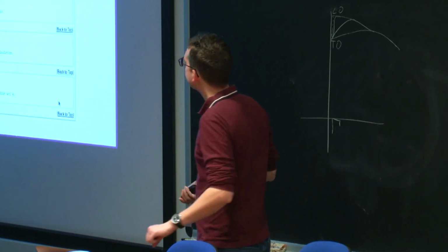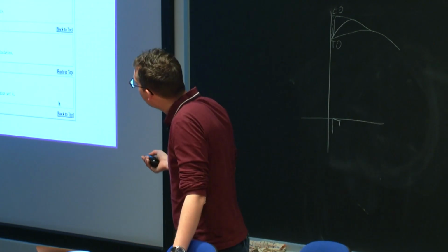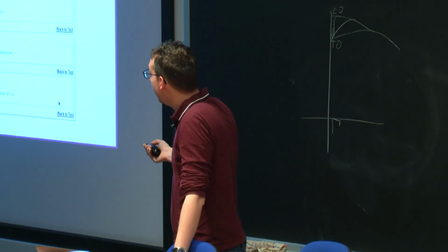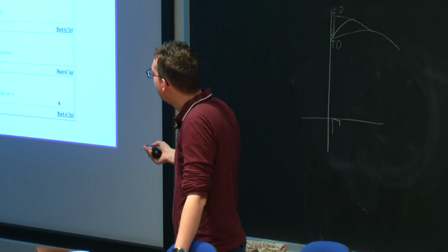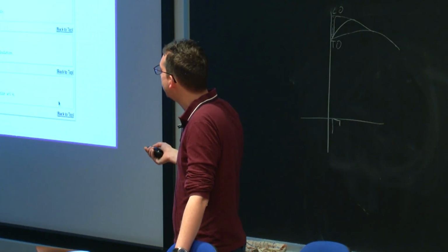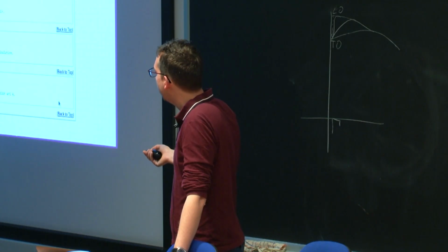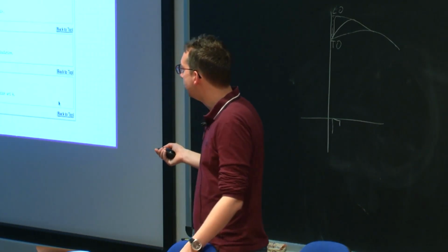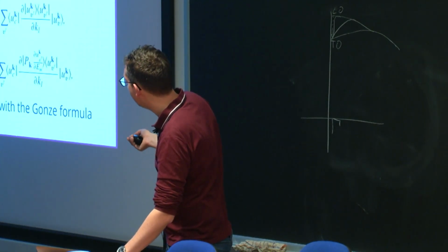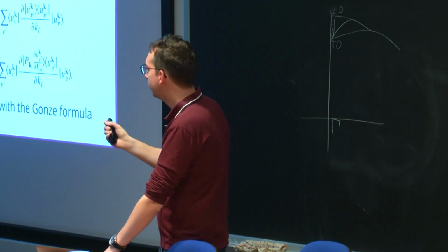So how do you compute the Raman tensor in practice? You set raman equal true in the input of phonon, and then you have three additional variables that you can use. One is the threshold for computing the variation of the wave functions, and then you have a threshold for the non-self-consistent calculation, because when you're doing this derivative here, you need to compute the wave function at k and k plus a small q.